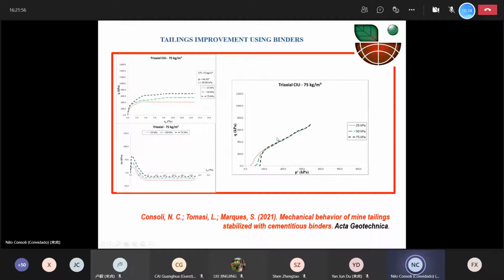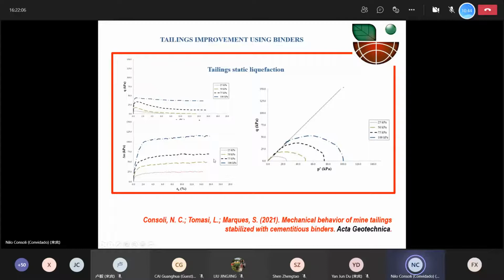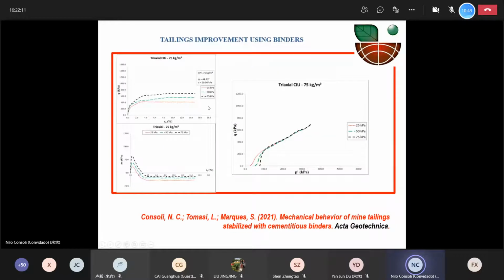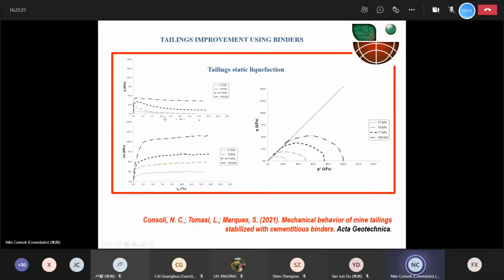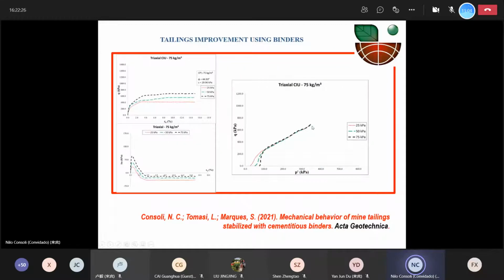In order to try to solve this problem, we thought about using some binders to improve the material. So this material that we have here that has such a behavior, after inserting some amount of cement, in this case 75 kilos per cubic meter, we turn the material from a material that is liquefiable to a material that is completely changed. I mean, you have some real cohesion, and so it does not liquefy anymore.